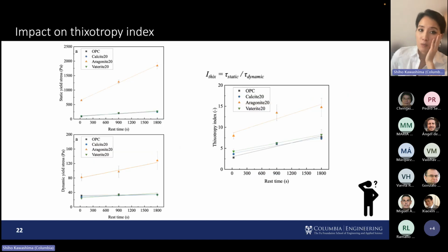We also looked at what some have called the thixotropy index. So just an idea of what is the relative degree of structural buildup versus structural breakdown, right? And so we have static yield stress evolution up here. So this is the same result as the previous slide. And then dynamic yield stress evolution at the bottom. So remember, that's your steady state in your flow curve.